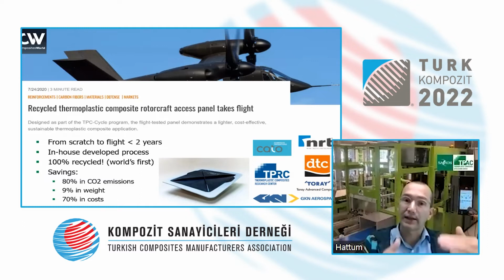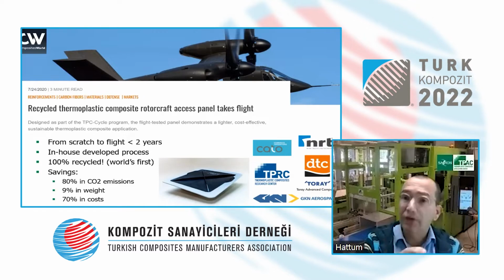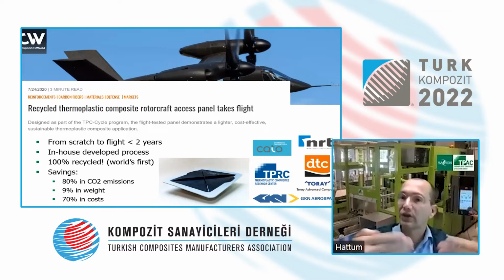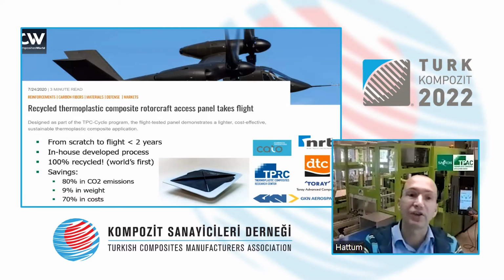The process that allowed for the recycling without fiber breakage and good mixing of these parts was completely developed in-house. The panels themselves that are on the tail sections, they are 100% recycled, which is a world first. So there is no virgin composite material there. And the most impressive part in this case is that we managed to do all of this with 80% CO2 emission reduction, but also 9% weight reduction, which is strange because the recycled material, shorter fiber, random orientation, in principle should have lower properties than the virgin material.